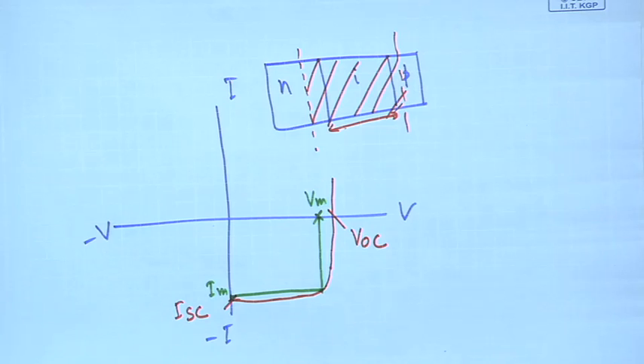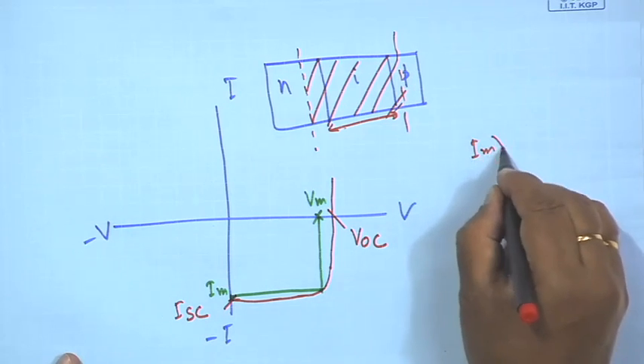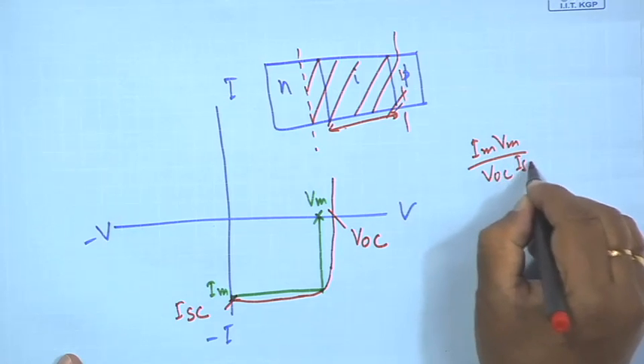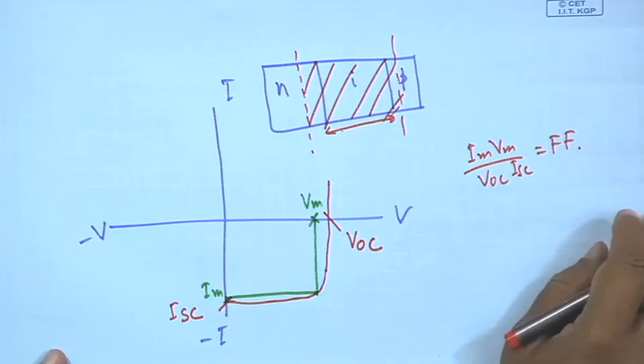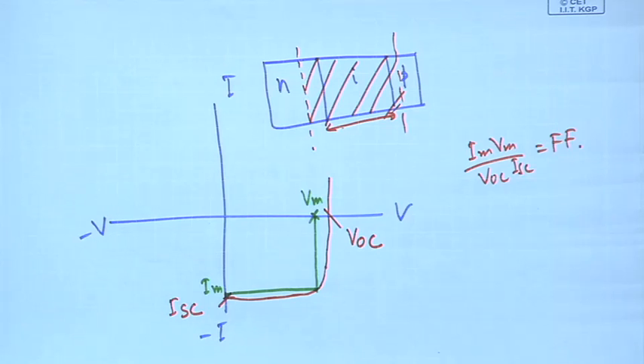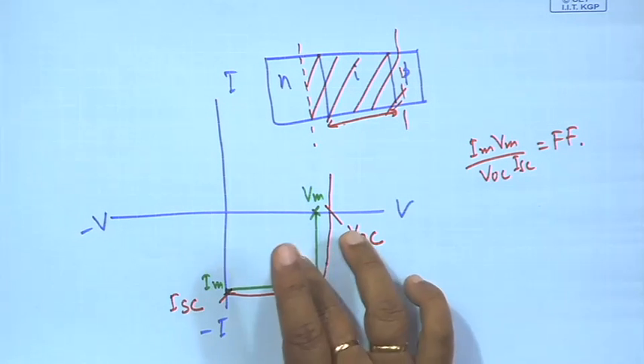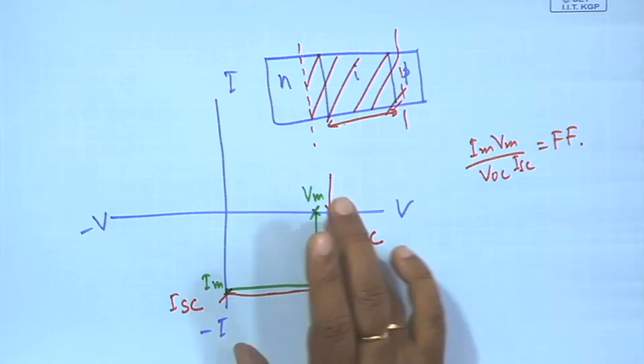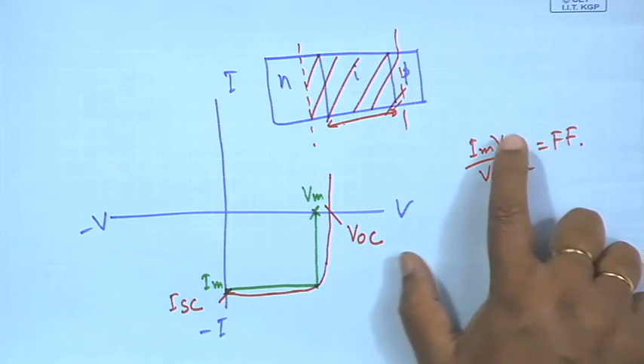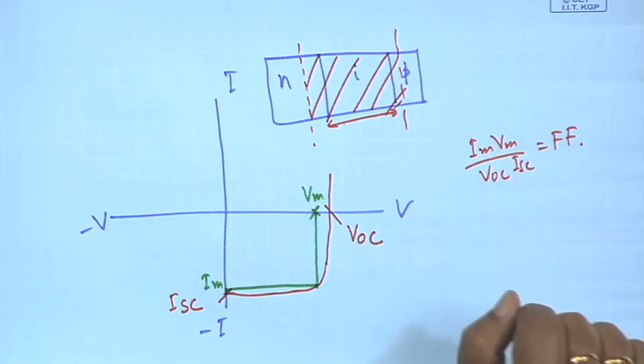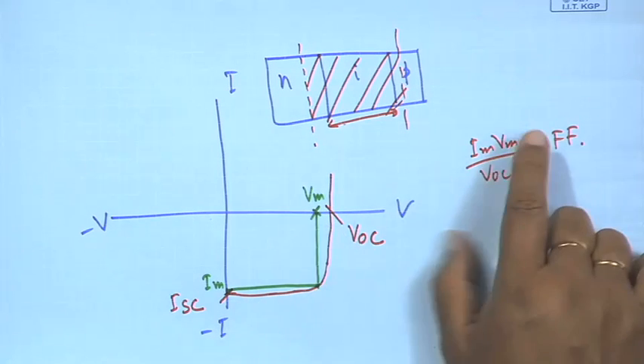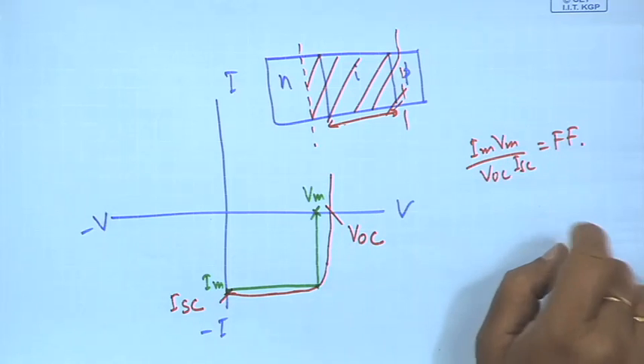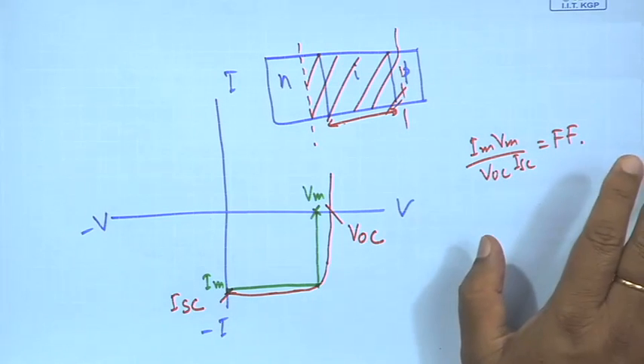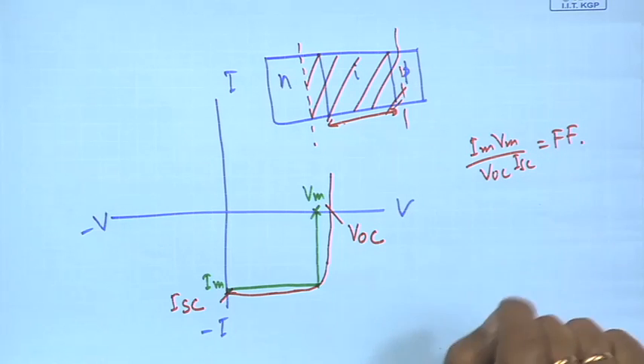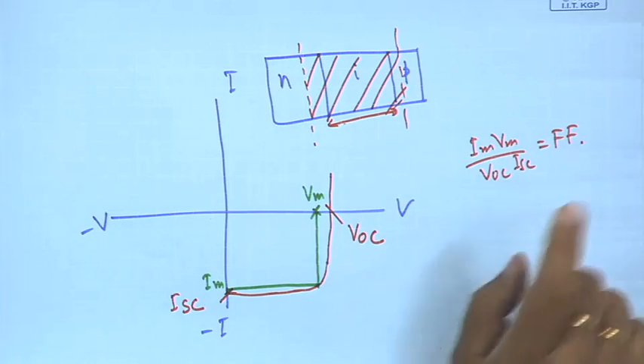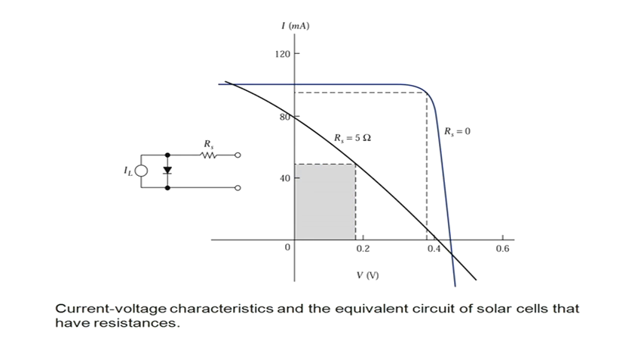That means the load can draw, and this IM VM by VOC ISC parameter is known as the fill factor. The fill factor denotes how close the characteristic is to the maximum power rectangle. When both are equal, the fill factor will be almost 100%, but the IM VM product will always be less than VOC ISC, so the fill factor is always less than 100%. In normal cases, it can be 70 to 80%, for a very good solar cell characteristic.